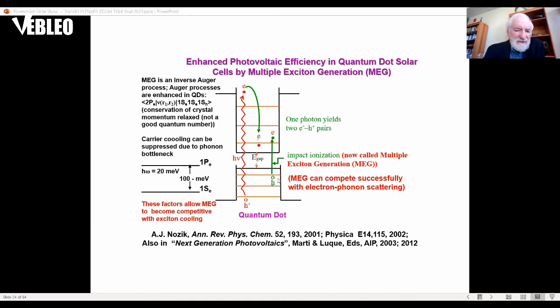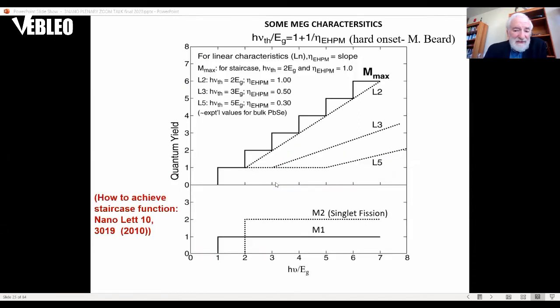Then you can slow it down and allow this beneficial process of creating multiple electrons per photon, called MEG, multiple exciton generation, because the exciton is created from having the electron and hole confined in this nanoparticle. There are different characteristics, but in the ideal case you want a staircase function, so that every time a photon is n times the band gap, you'll have a quantum yield of n. So if you're, say, 3 times the band gap, you'll get 3 electrons per photon in a single steep step like that, and so forth. For n times the band gap, you'll get a quantum yield of n.